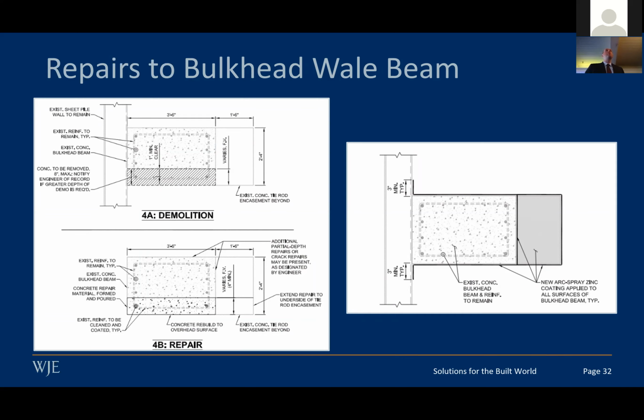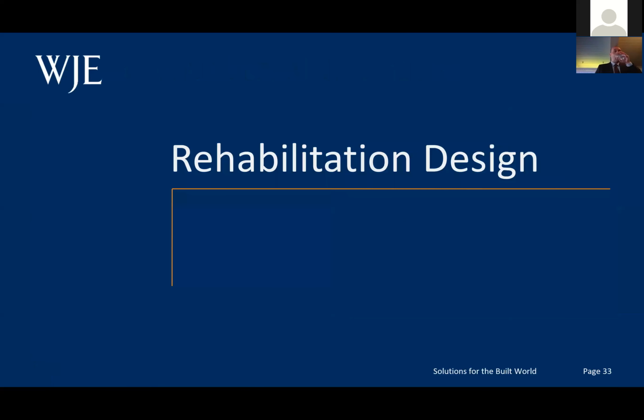But to provide further cathodic protection, we detailed a zinc sprayed applied coating to be applied to it. So the zinc gets consumed as chlorides penetrate rather than the steel itself. And so this is another mechanism of providing long-term repair.